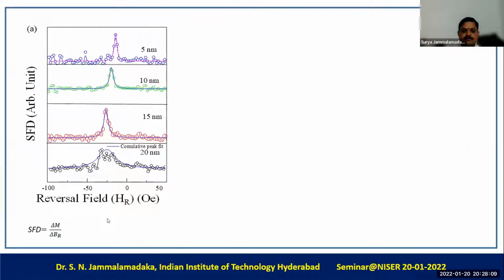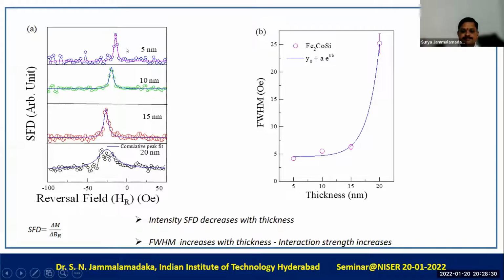We also plotted the switching field distribution with respect to the reversal field. What we could see is that the switching field distribution intensity decreased from 5 nanometers to 20 nanometers. This also endorses that the magnetostatic interactions are more and more as you go to higher thickness. And if you look at the full width at half maximum, it increases with the thickness, again endorsing the increasing strength of the interaction between the magnetic grains.